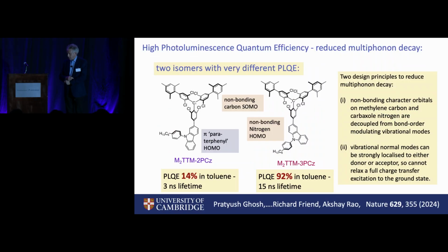So why are they so bright? This is a small deviation from the thread of the talk that I want to take you through. But we were puzzled. What our materials seem to do is to buck the trend of what's called the energy gap law. That as you head from blue or green, where you can get very luminescent materials, to red and infrared, molecular systems just stop glowing. And the reason in general is that because we have lots of high-frequency vibrational modes, the carbon-hydrogen stretch at more than 3,000 wave numbers, it doesn't take many vibrational quanta to get you right across from the electronic excited state back to the ground state. And as you go to lower energy excited states, as you go to the red and the infrared, that takes over.